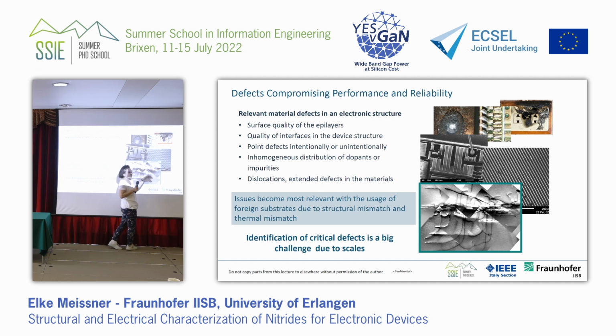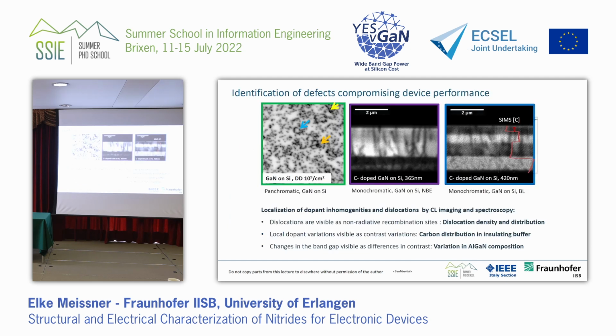So it's getting larger and larger. Then you have the size of the whole wafer with many devices. And you have the whole crystal, which gives you many wafers. So the scales get larger and larger. And to follow the whole chain from the beginning to the end, this means that you have to observe all the problems on different scales. I show you an example of depletion of dopants in the carbon-doped buffer in a gallium nitride HEMT and what it's doing to the HEMT.